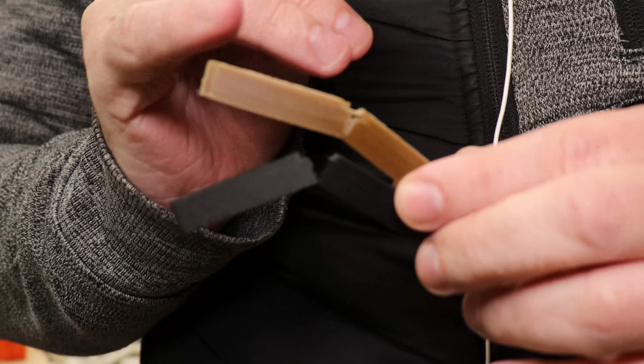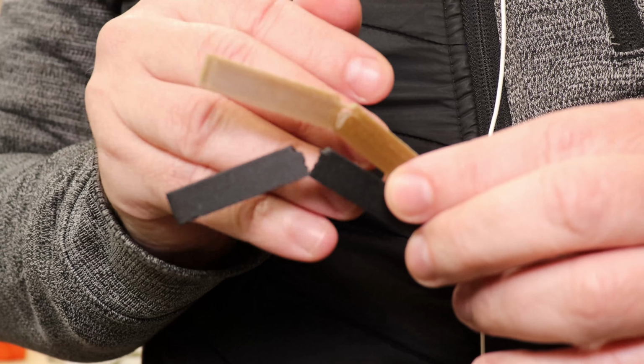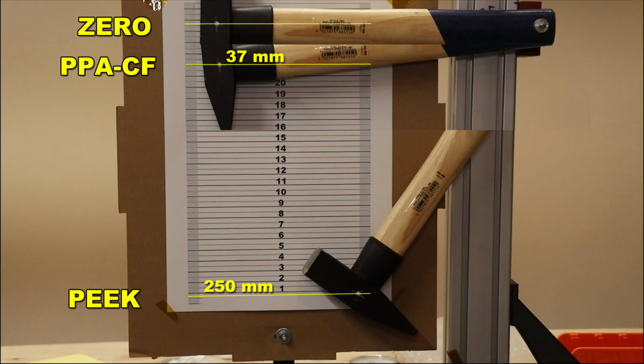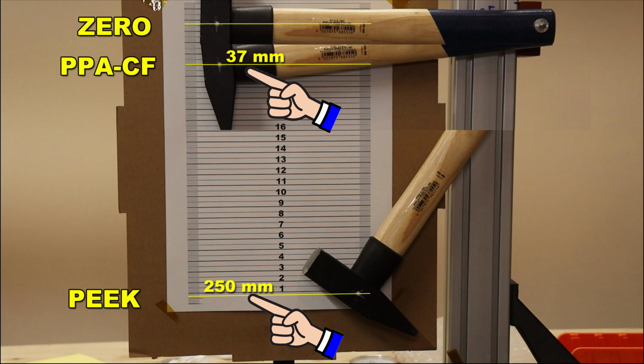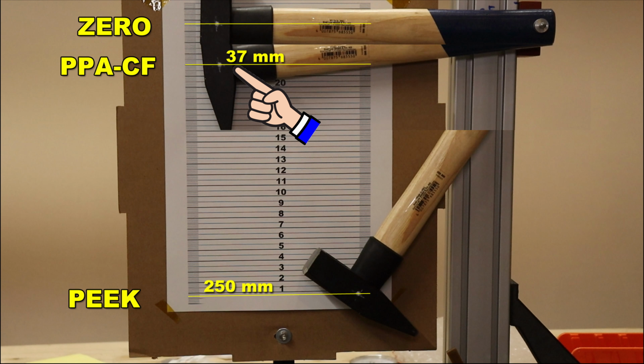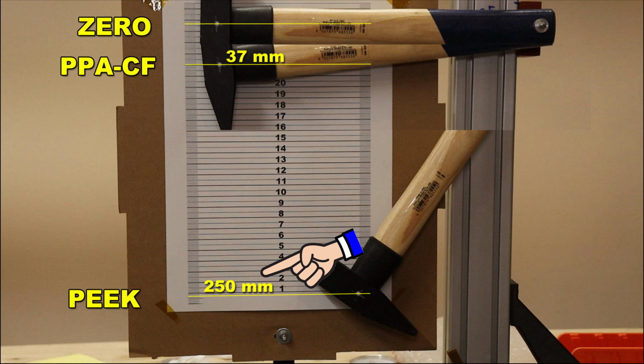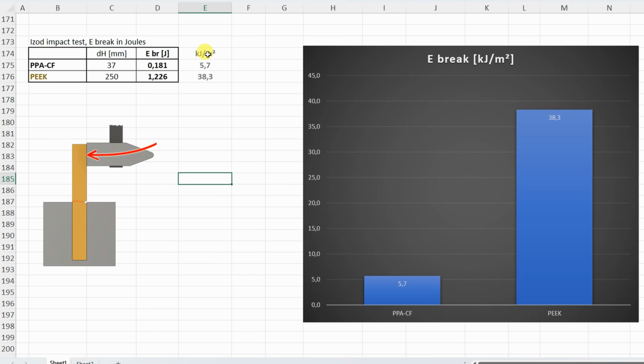And the first test where the PEEK was better than the PPA-CF. These are edge positions of the hammer, and here you can see the difference in height. This means PPA-CF is quite brittle material and PEEK is quite tough. And here you can see the calculated breaking energy in kilojoules per square meter.